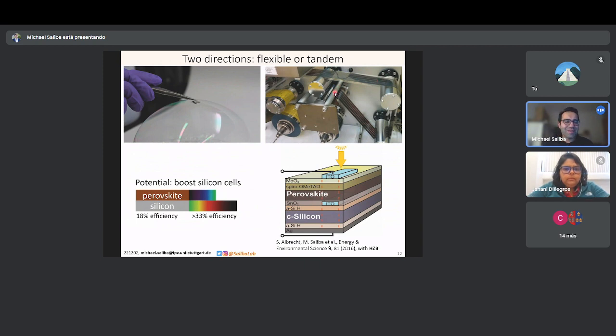The second big direction is, of course, to try to assist silicon that is now covering the market with 95% by putting a perovskite silicon tandem. The perovskite layer can filter out the blue light, turn it into electricity without much internal thermal conversion. And then the silicon can take care of the red part of the sunlight, turning it very efficiently because, again, little internal thermal conversion into electricity. So you can double dip into the sun spectrum that way. And because they assist each other, it's called a tandem.